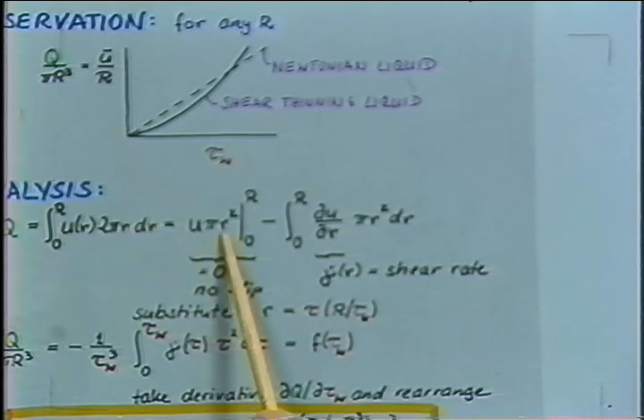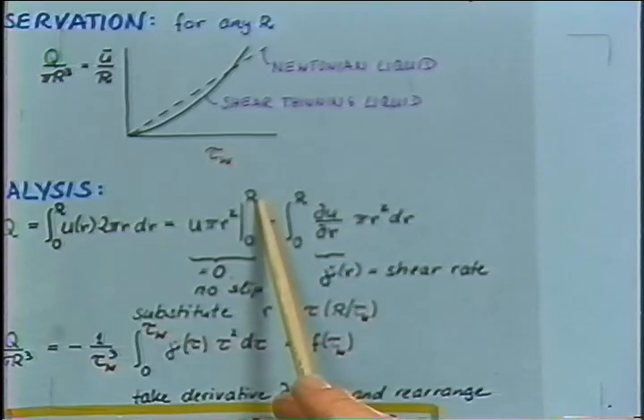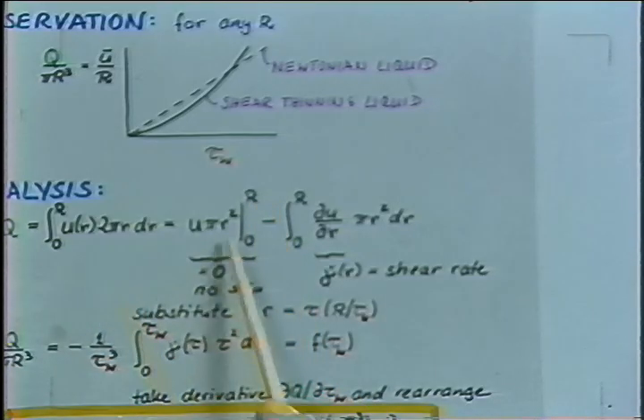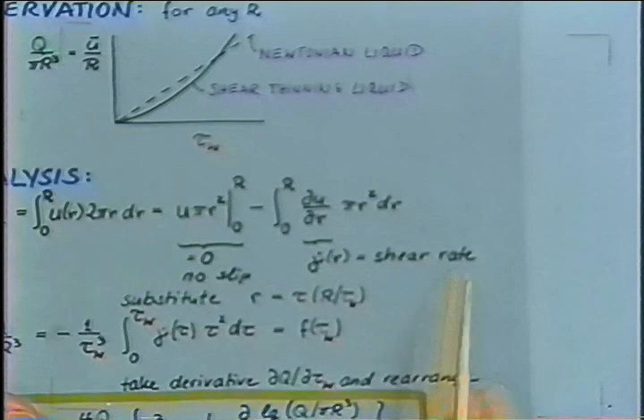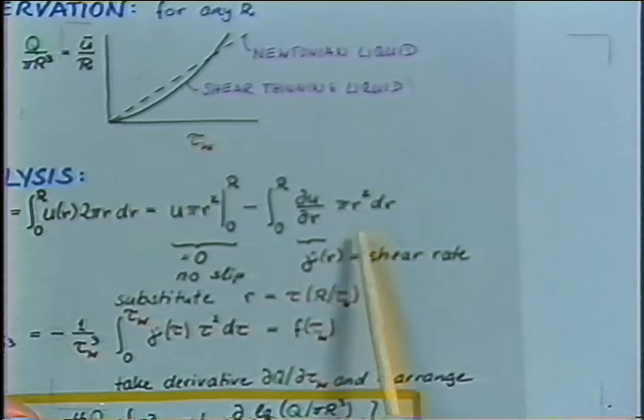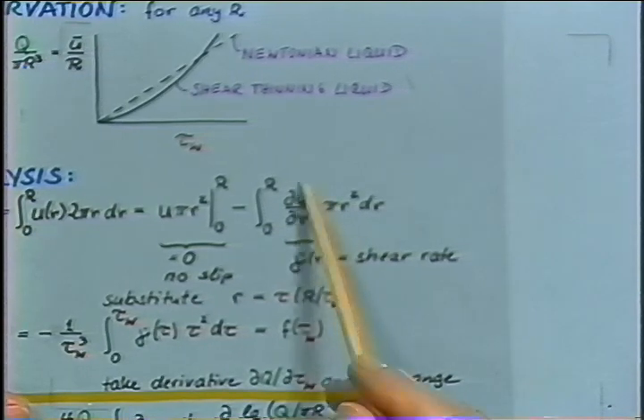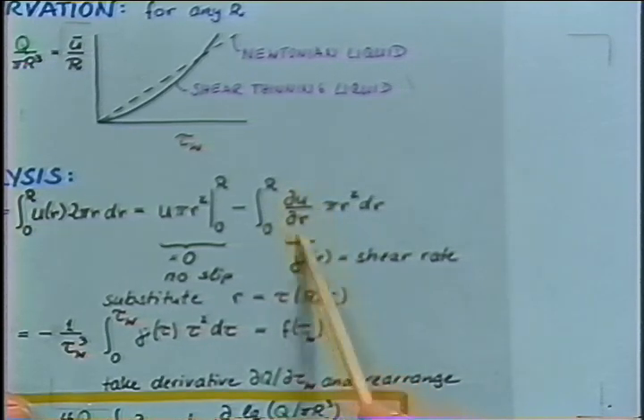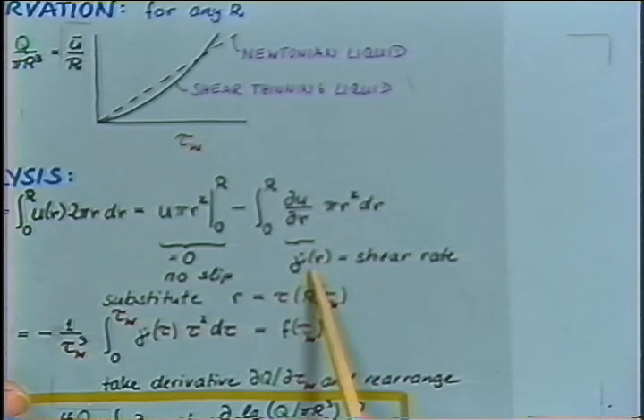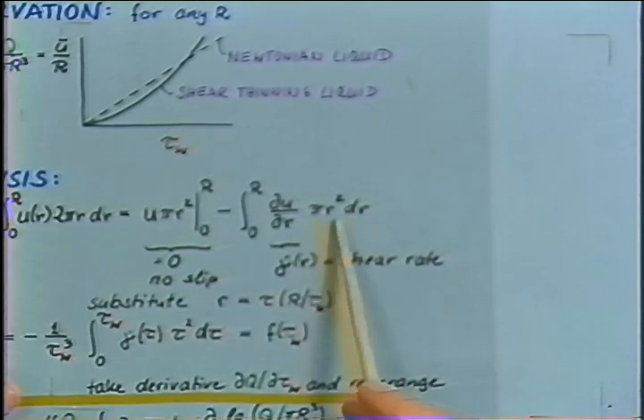The velocity in the center is high, but the radius is 0 in the center. At the wall, the velocity is equal to 0, and the radius is high. So at both limits, this function is equal to 0, provided that we have a no-slip condition. So the no-slip condition enters into the analysis. We have to keep this in mind. The remainder here is a function. This is the function we are looking for, the shear rate as a function of the radius, multiplied with pi r squared dr, and this integration.